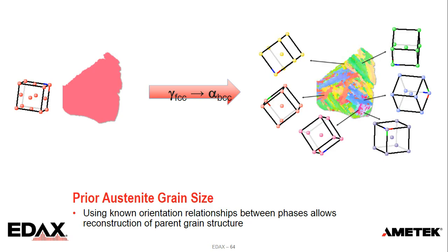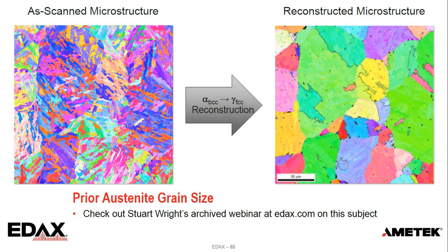But essentially, what's happening is we start with our austenitic FCC phase at higher temperatures there on the left, and as it transforms through the transition temperature, there are different possible orientation relationships between the FCC austenite and the BCC ferrite. So it can transform by certain rules and rules with tolerances. But if we know those and we put those into the software and we do some permutations, we can reconstruct the microstructure. And that's kind of an example here going from the as-scan microstructure to the reconstruction microstructure on the right.